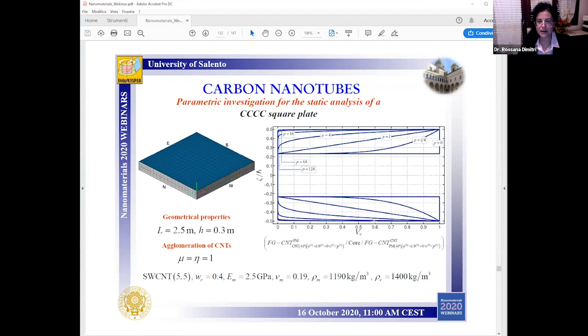Where the external sheets are uniformly reinforced by carbon nanotubes, assuming a fixed mass fraction for the reinforcing phase equal to 0.5. So since mu and eta are equal to 1, the nanoparticles are uniformly distributed in the matrix, and a 4-parameter law is applied now to the carbon nanotube volume fraction in the external sheets to show the influence of the through-the-thickness distribution of the reinforcing phase. So on the right side of this slide, you can notice the volume fraction distribution of the carbon nanotube reinforcing phase along the thickness of the structure for different values of the exponent P.